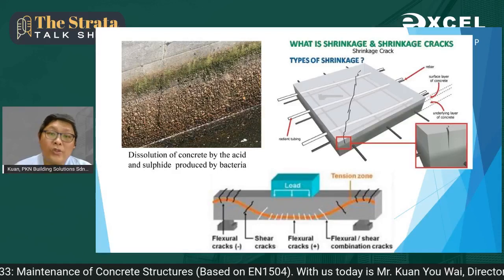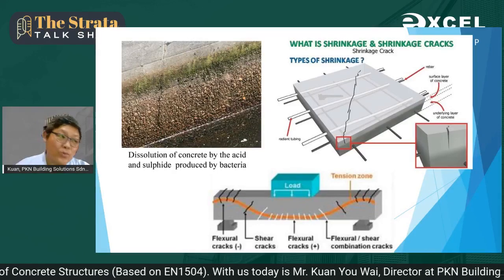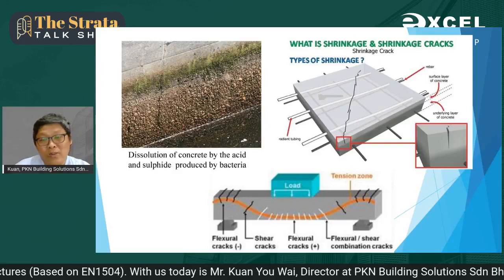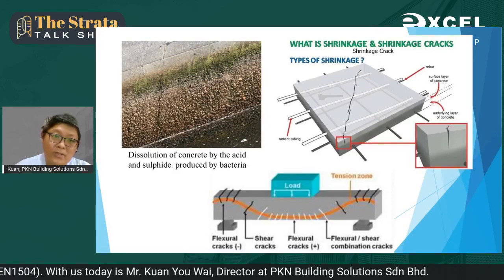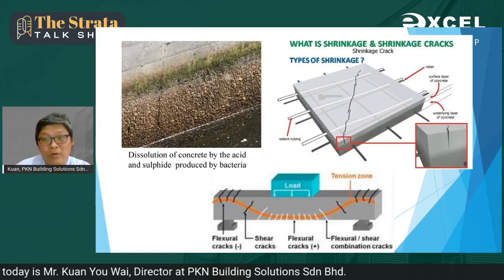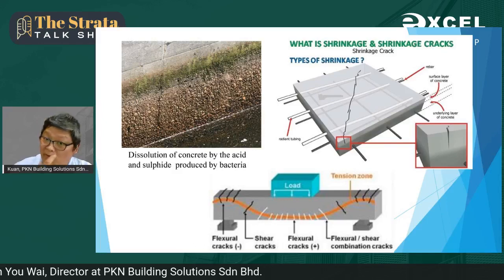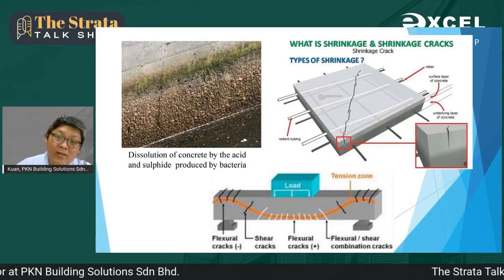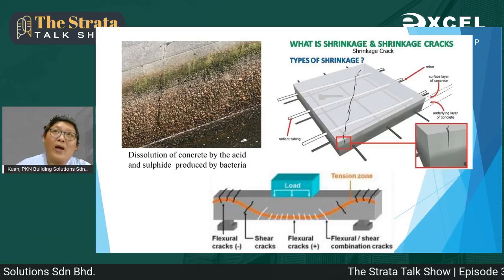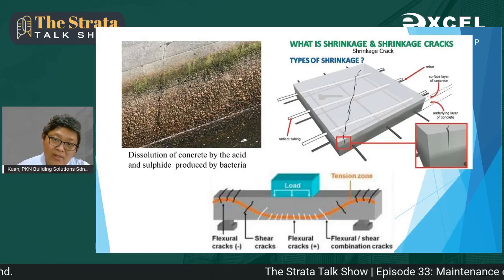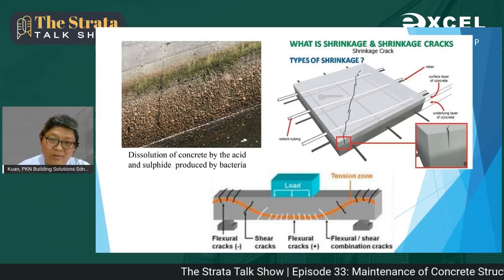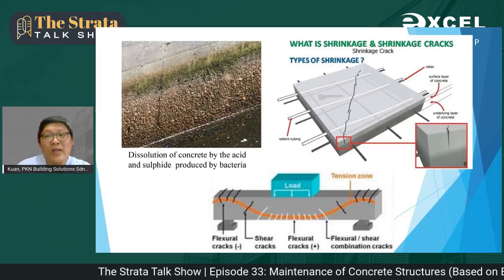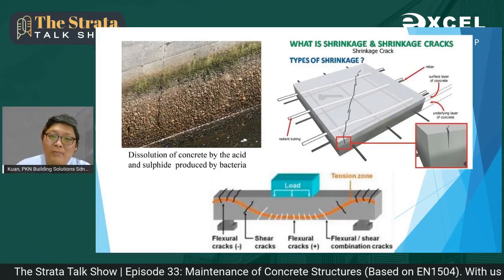But natural type of shrinkage due to the evaporation of water. Water actually comprises 30 to 40% of our concrete originally. So when the water evaporates, it will shrink naturally, and such shrinkage will be evidenced by the natural shrinkage crack like this, which has no structural concern, but it needs to be repaired.